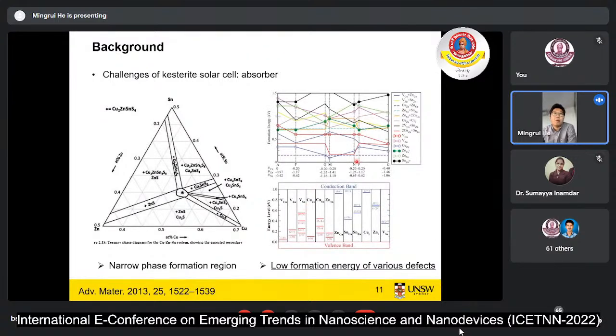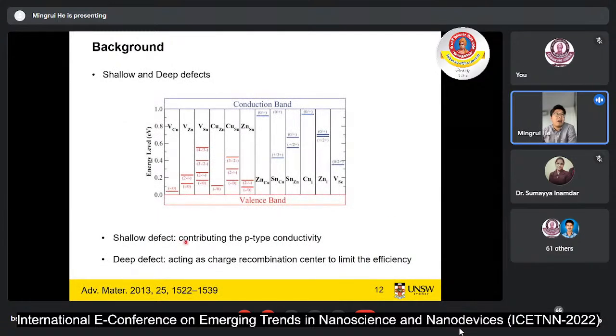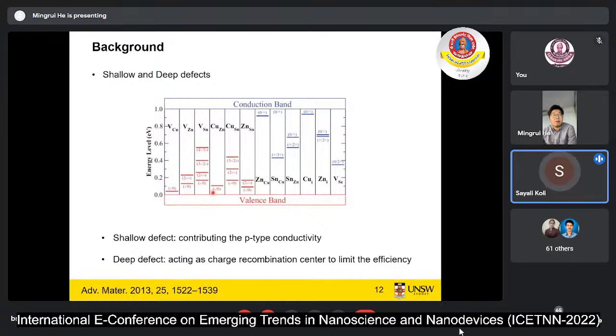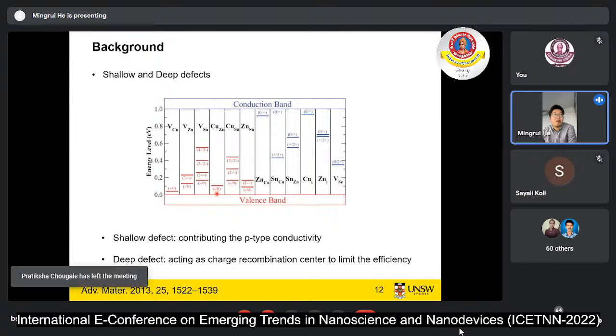As we can see from here, we can form various defects, but also some defect clusters. Some of the defects are good, some of the defects can be very bad. For example, the shallow defects, like here, should be the copper vacancy and copper zinc anti-site defects. In CZTS kesterite materials, these two defects actually contribute to the p-type conductivity. So if we get much more of these defects, our CZTS materials can be improved a lot.